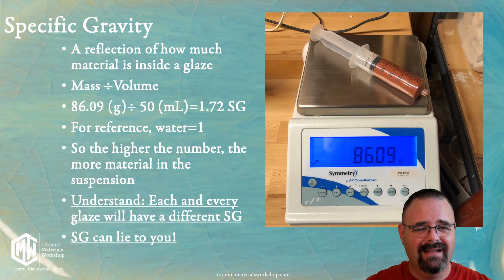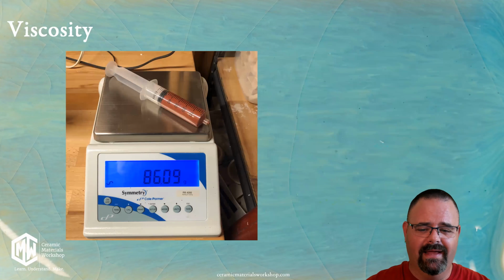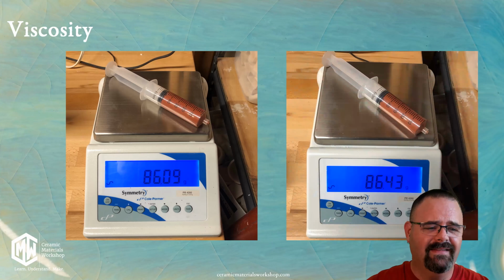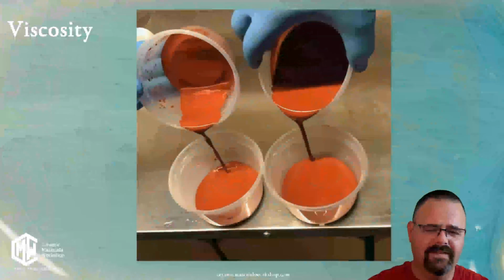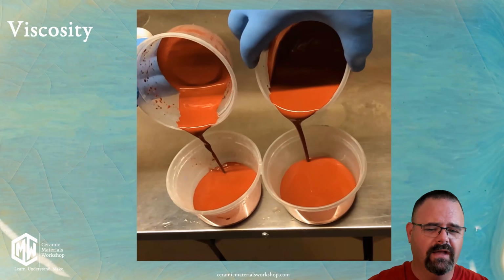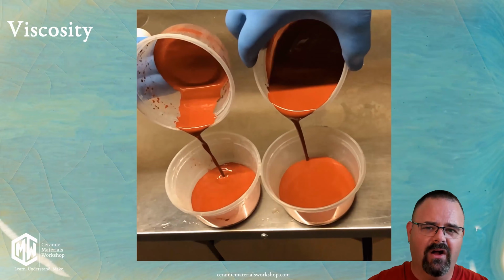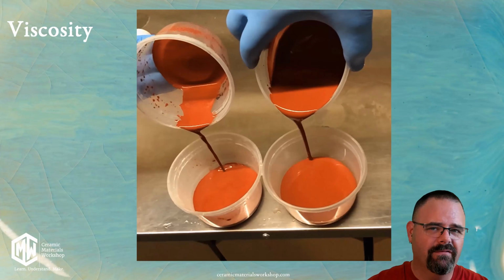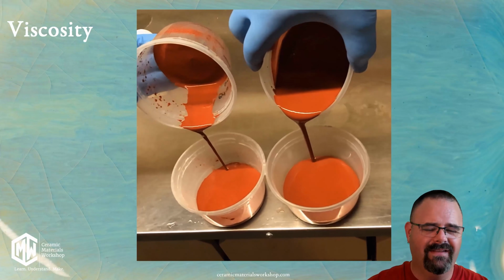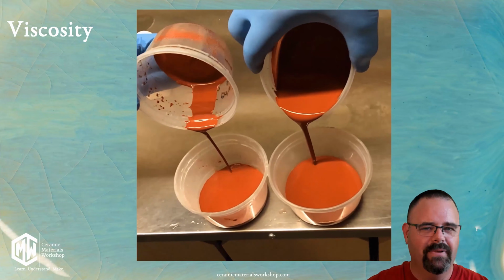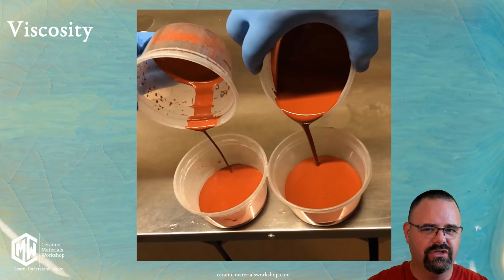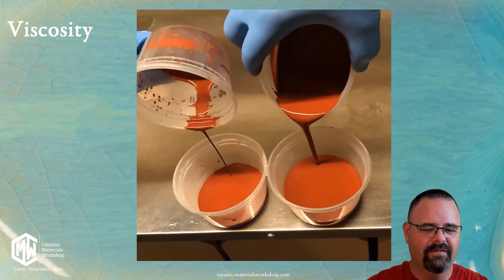And it's not. You see, here is that same glaze with a specific gravity and its weight is 86.09. Here is a second glaze whose specific gravity is essentially the same, right? Two different glazes with relatively the same specific gravities. But here's the problem. This is a video of those two glazes pouring in slow motion. Now you can see the glaze on the right is very, very thick, but the glaze on the left is very thin like water. But these are the two glazes I just showed you with exactly the same specific gravity.